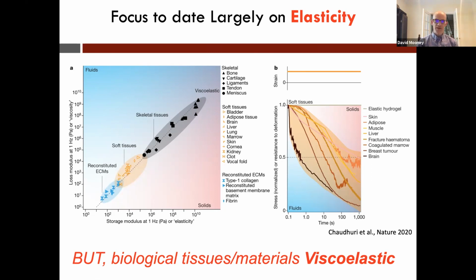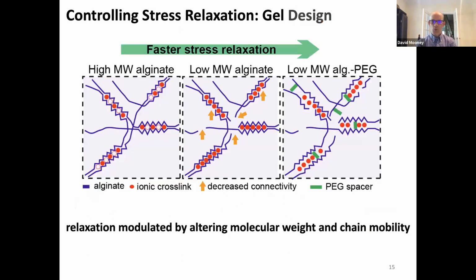So we became very interested in how cells actually interpret the viscoelastic properties, and whether they care about this time-dependent mechanical behavior of the materials surrounding them. One really simple way to regulate the rate of relaxation in the design of these hydrogels is to control the molecular weight distribution. The higher the molecular weight, the more entanglement one gets, and the more elastic the material will behave. We can also conjugate small PEG molecules onto the polymer chains that in essence act as plasticizers and will increase the viscoelastic behavior.